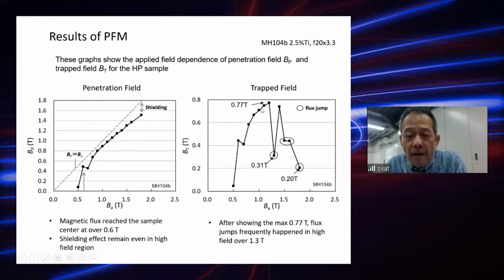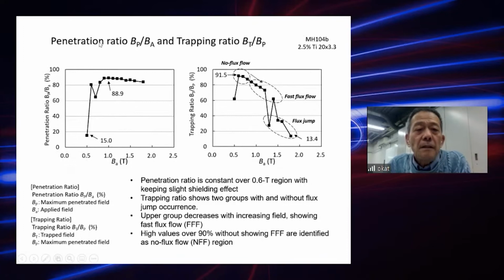As for the BT trapped field, after showing the maximum value of 0.77 Tesla, flux jumps frequently happened in high field over 1.3 Tesla in this sample. These circles show where the flux jump happened. It is very characteristic that we don't see any flux jump at this point at the 1.4 Tesla application. So it is very interesting.